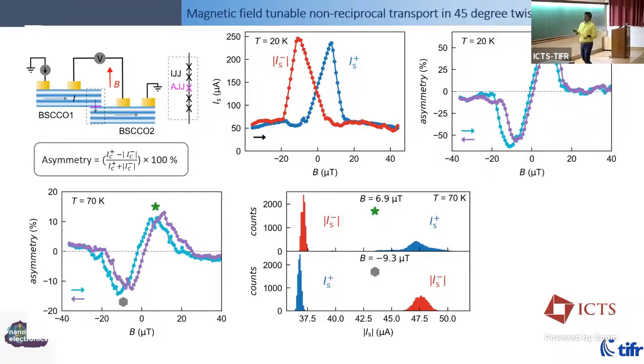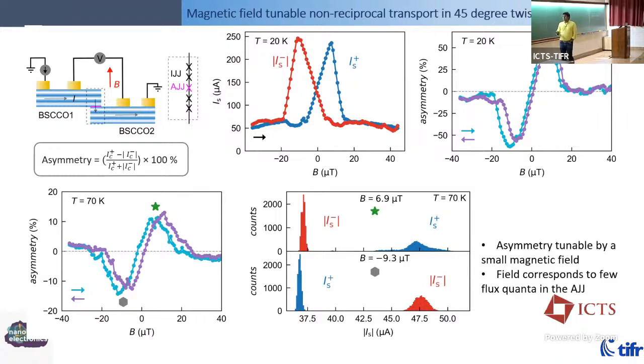And there's an overall symmetry of the problem, not just in terms of the asymmetry, but in the switching distribution. So the switching distribution of plus side and minus side is different, which is kind of central to why this device works as a diode, and I'll talk about it. But when you flip both the current and the magnetic field, you get the same thing, which is required. If the system breaks this kind of symmetry, then there is some problem in the experiment. So this magnetic field actually corresponds to a few quanta of flux through this Josephson junction, order of 1 or 2 or 3 flux quanta, that can tune the polarity of this Josephson device.